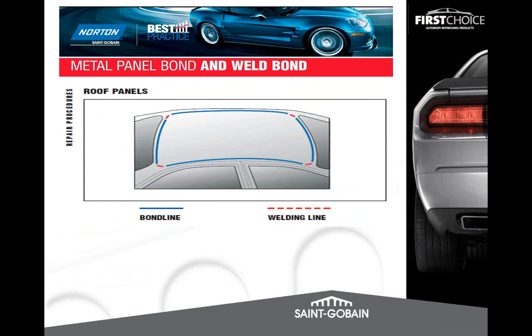When we look at, and I mentioned this earlier, a roof panel, the OEM wants you to tack the corners into place, but everywhere in between can be glued. So a 75-minute or a 90-minute glue, either an acrylic or an epoxy, can be used. Obviously, the advantage of the acrylic, as I mentioned, is it can be welded through at any time during the repair. So if I got glue in the corners where I had to tack weld it, if it's an acrylic, I'm fine. If I use an epoxy, I better do it when it's in its wet state or stay away from the glue by a couple of inches, if possible. And this is, once again, what most OEMs recommend.